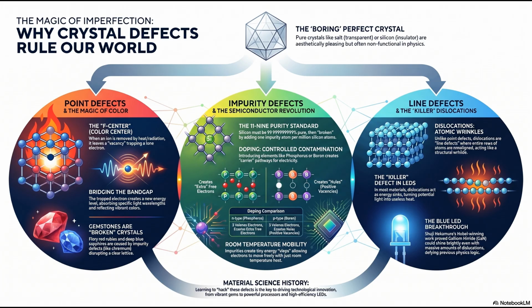Because gallium nitride is notoriously aggressively hostile to being grown as a perfect crystal film. It is a metallurgical nightmare. What happens when they try? When scientists tried to grow thin films of GaN on a sapphire substrate, the differing atomic spacing between the sapphire and the gallium nitride caused immense structural stress. The growing crystal would inevitably tear itself apart at the microscopic level. Oh no. Every single time they grew it, it was completely riddled with line defects. The killer defects, the wrinkles, the sinkholes.